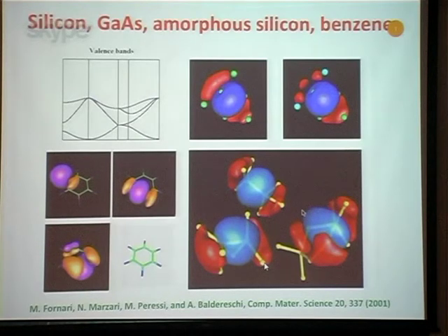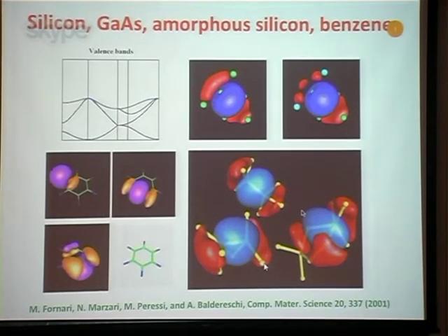Or sometimes they use much shorter simulation like ab-initio molecular dynamics, but then they do some Monte Carlo steps in which they try switching atoms that are very poorly coordinated to see if slowly you can reach a more meaningful four-fold coordinated amorphous configuration. But the issue on how to obtain a meaningful structure of an amorphous crystal is in itself a very complex problem, and for which there isn't a single satisfactory solution.